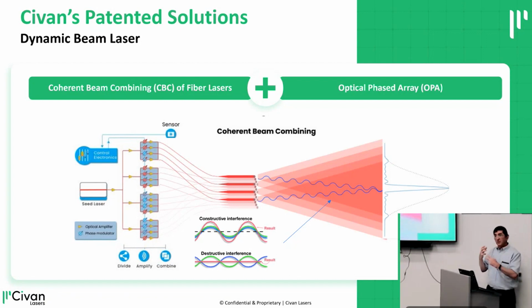But because light is waves, when you have multiple sources that are coherent to one another, meaning they're all the same wavelength and they're all correlated to one another, if you have two waves that come in the same phase, they add up the energy. And if they come with opposite phases, they cancel one another. So what happens is that in some areas in the center, because of symmetry, they all come and add to one another. And in other places, they come out with different phases and basically cancel one another.